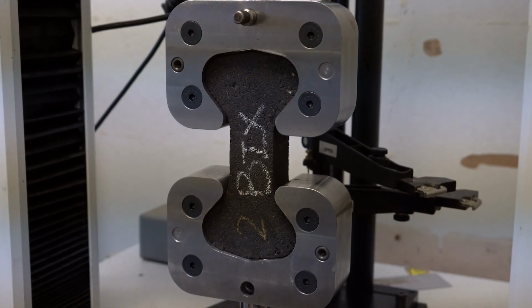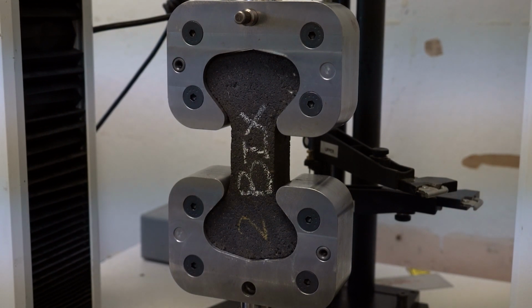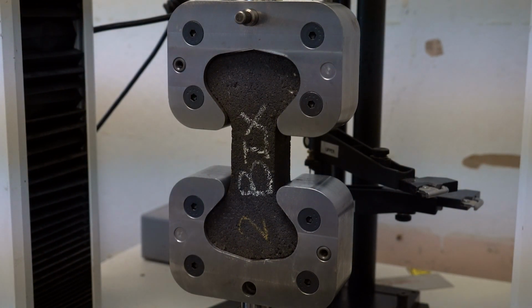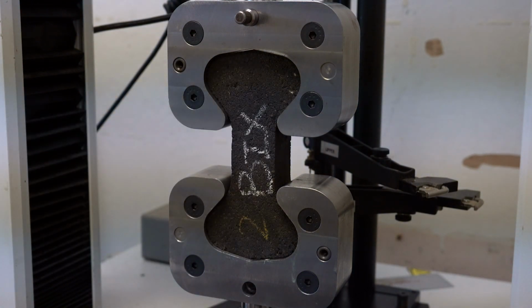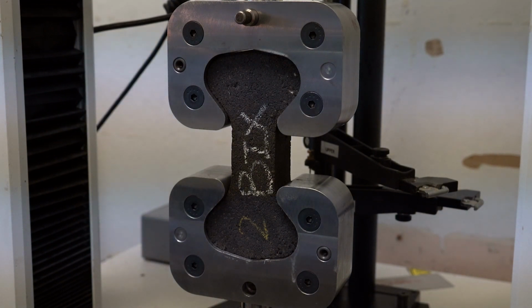Conventional asphalt has little to almost no tensile strength, but for epoxy asphalt, we have a very high tensile strength, and this is one of the ways we do the tensile test. The speed of it is 0.2 inch per minute until failure.